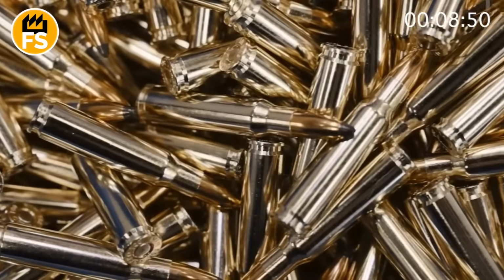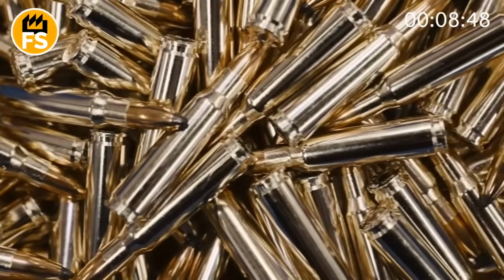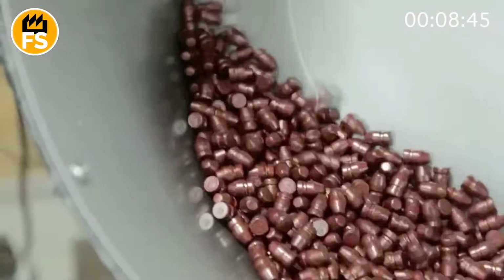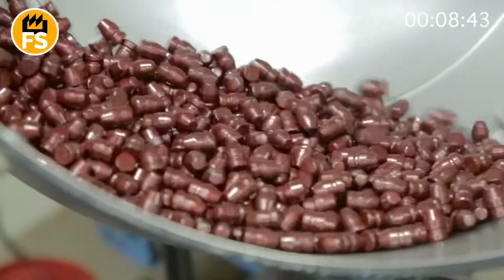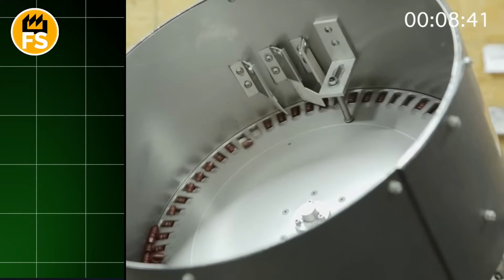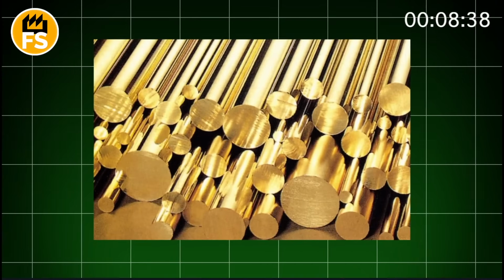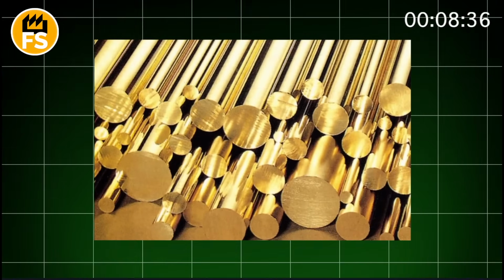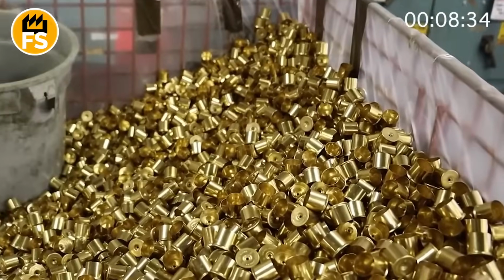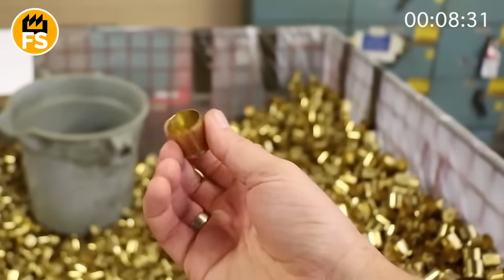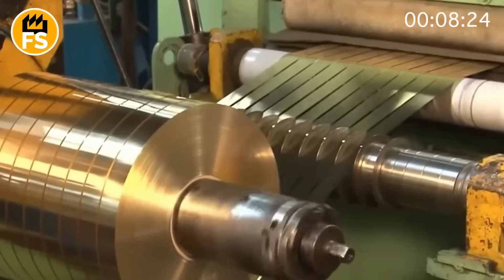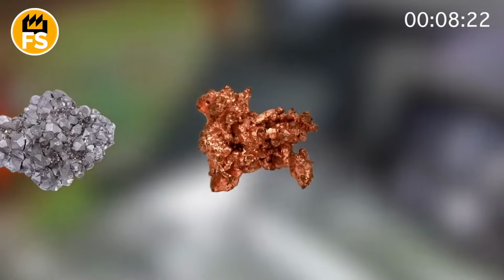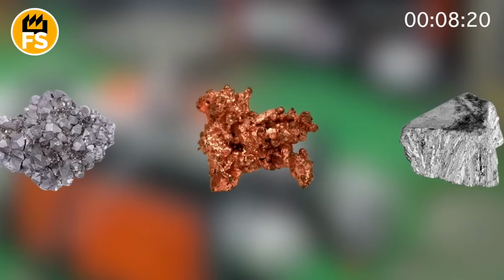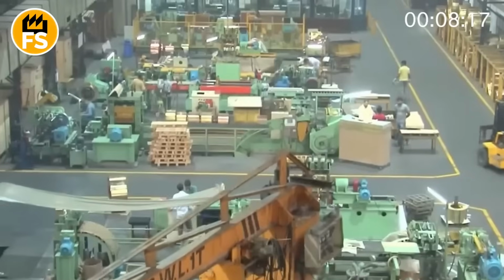Hundreds of millions of bullets roll off factory assembly lines around the world every year, and each one passes through quality control lines with micron-level precision. The primary material is brass, an alloy of 70% copper and 30% zinc. It's ordered in massive rolls about 0.06 inches thick and weighing up to 6,000 pounds. These rolls are supplied by metallurgical plants, most often in the United States. These are companies like Olin Brass or Chase Brass. The rolls arrive in sealed packaging to prevent oxidation during transport.